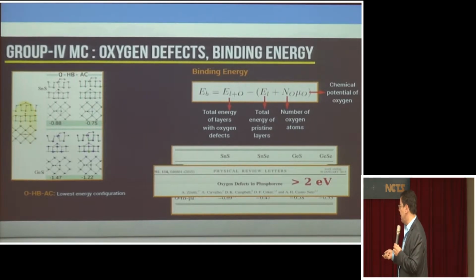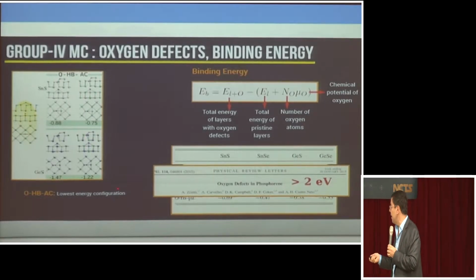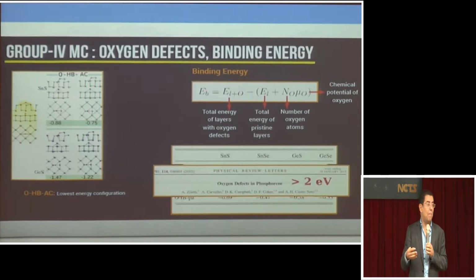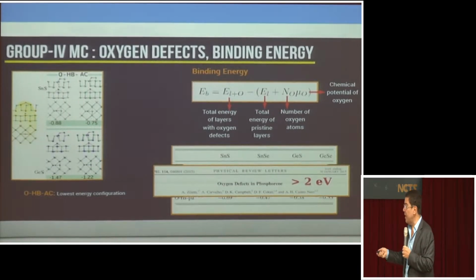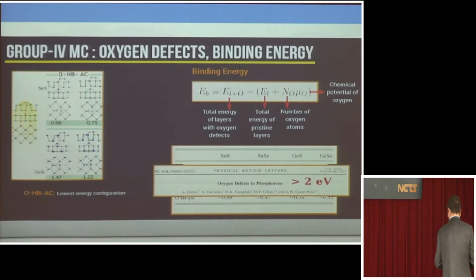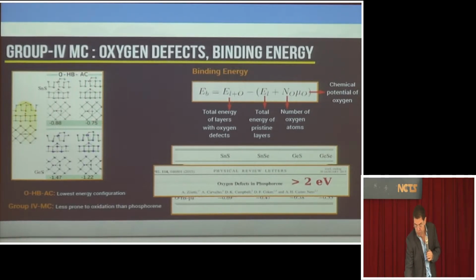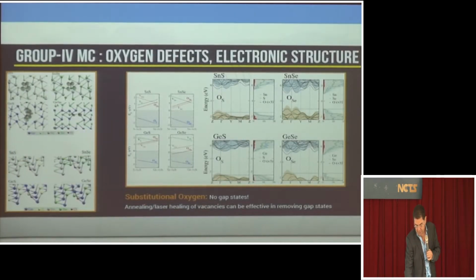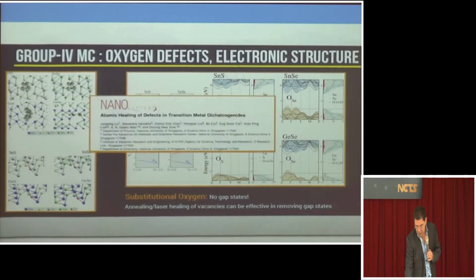Okay? And in fact, when you compare the energy for oxidation of these oxygen defects, the energy for oxidation in, say, something like germanium sulfide is much higher. So in fact, these materials are very stable in air. Okay, if you take black phosphorus and leave it half an hour in air, it's gone. But these materials can remain in air for a long time. Okay, and we can explain that using band structure calculations, by looking again at defects. So again, defects in semiconductors is something to understand. It's very important, so you can explain things that are hard to understand without doing these calculations.